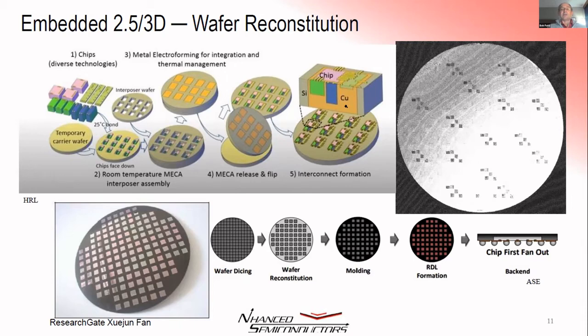There are other forms of wafer reconstitution technology around. Several of them have to do with putting die inside of silicon pockets or injection molding die that are on a temporary carrier, and you can mold around the die. ASE does this. A number of packaging, quintessential packaging companies do this type of thing. This is actually something that NHanced has done. This is a DBI die to wafer assembly, and we backfill. So underneath this is an active silicon circuit. The die are then active silicon die bonded to it. The wafer is planarized and backfilled with silicon. So this is actually a completely planar wafer. This is a sonogram that was used to look at the devices after the bonding and planarization.